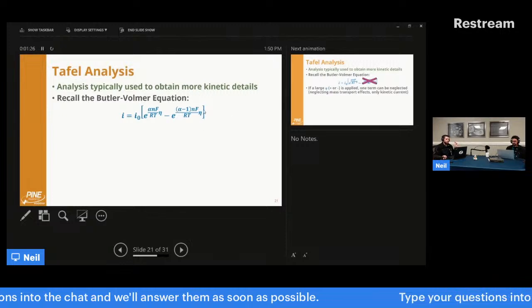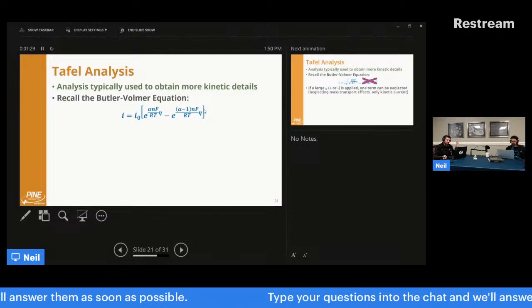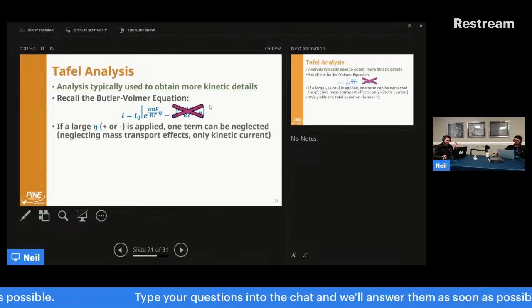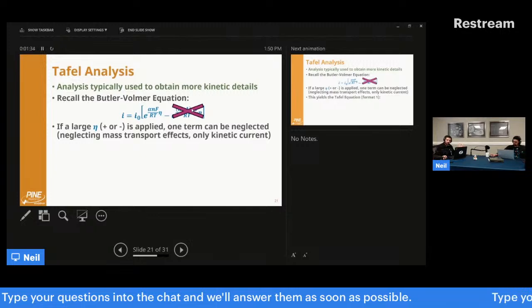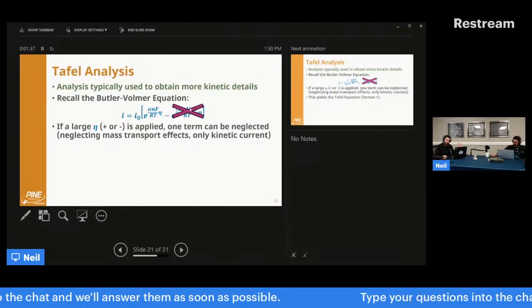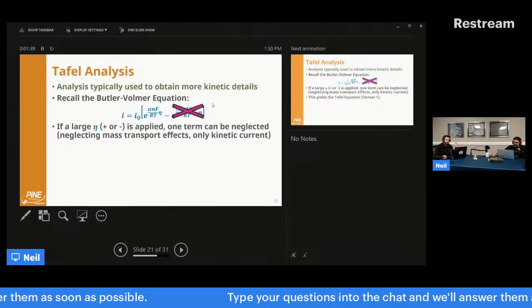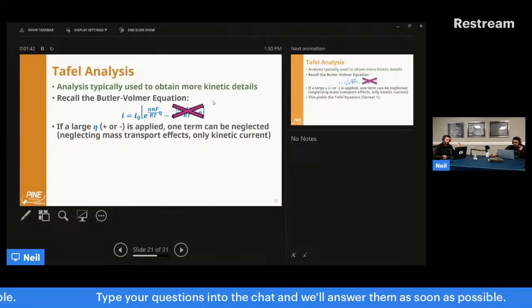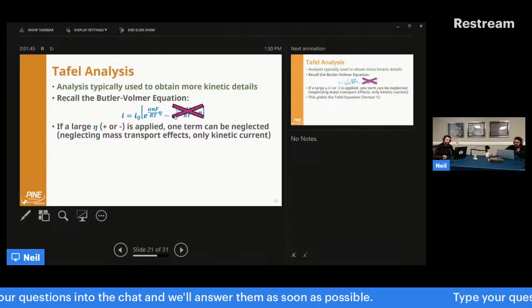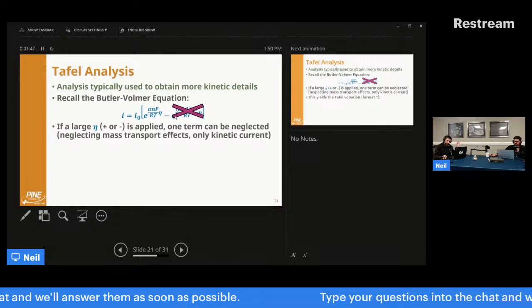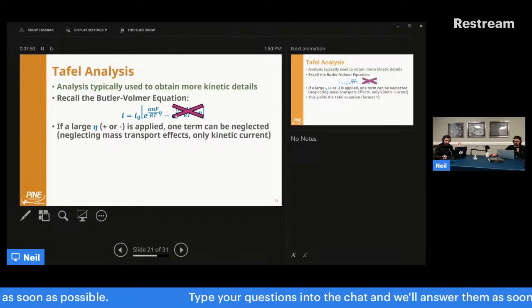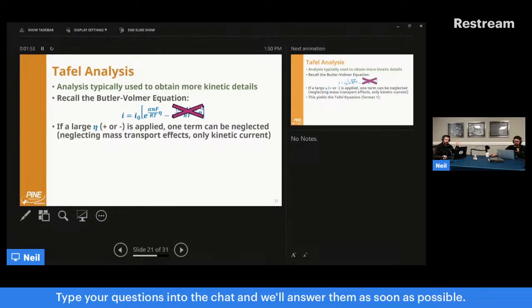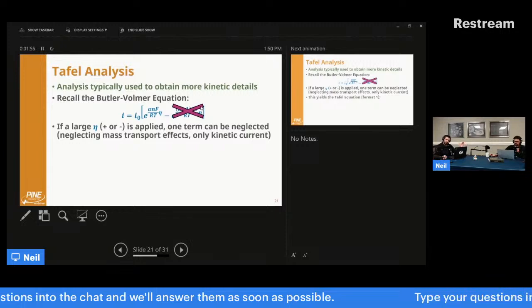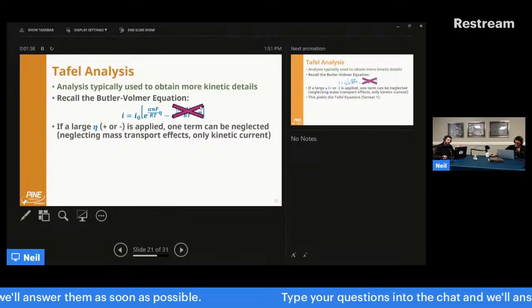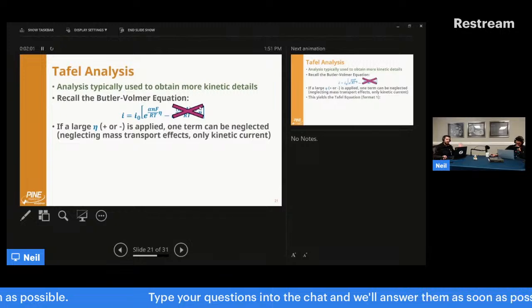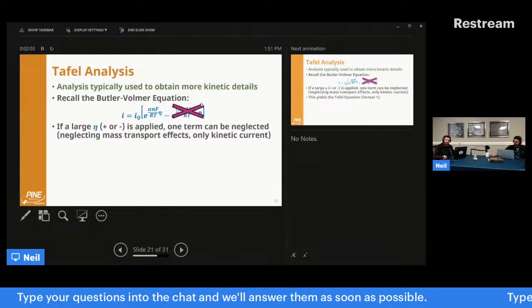So basically, what you do to obtain the Tafel slope analytically is we ignore one of these terms. If you recall Alex's just completed explanation of the overpotential, if we have a large enough overpotential, we effectively have less than 1%. This is for some perfect kinetic, thermodynamic, whatever process, whatever my E0 is. If I have a large enough overpotential in one direction or the other, I'm neglecting the oxidation or the reduction entirely, because it's only effectively 1% or less of that.